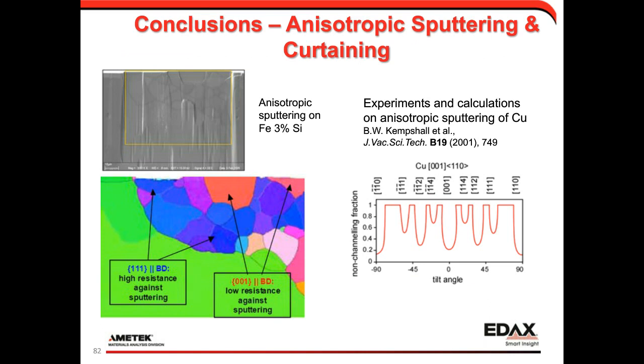So ion beams are a very new and efficient way of preparing samples. We want to monitor the incident angle in and the energy in to minimize amorphous damage that can be created. A couple of other things to be aware of, of course, is that the material removal rate will be anisotropic. It varies by orientation. This shows an effect here where in an iron silicon alloy, the 1,1,1 grains resist sputtering, the 0,0,1 grains sputter faster, and you'll see some surface topography develop if you etch that for a while, and that topography can again block your EBSD signal.